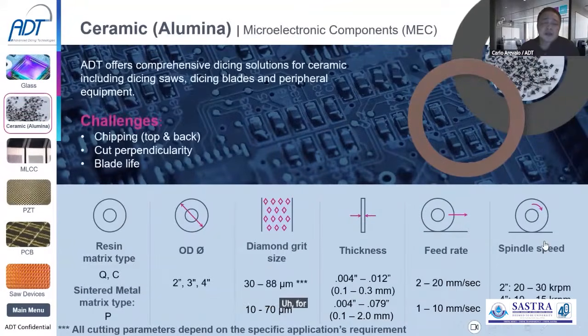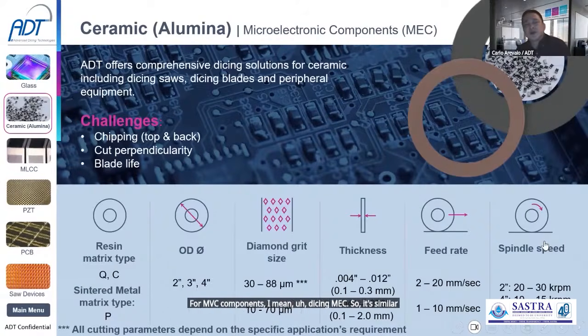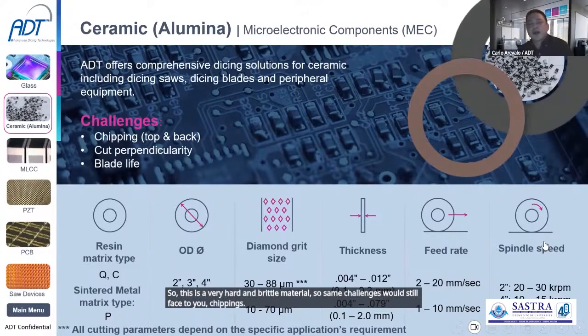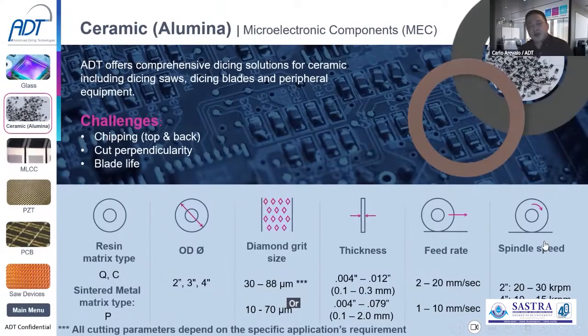For MEC, there's similar ceramic alumina for MEC components. I mean, dicing MEC. So it's similar to what I mentioned earlier. You're still dealing with a ceramic or with an alumina. So this is a very hard and brittle material. So the same challenges would still face you: chippings, cut straightness, I mean perpendicularity, or a short blade life. So all of these three things need to be optimized or considered in order to define the best blade matrix or formulation that you can use.